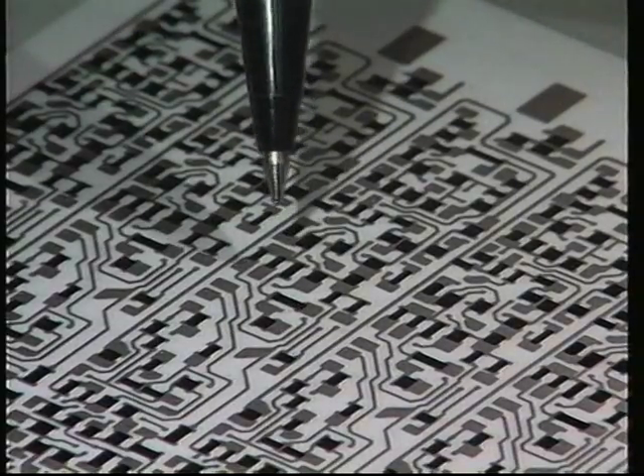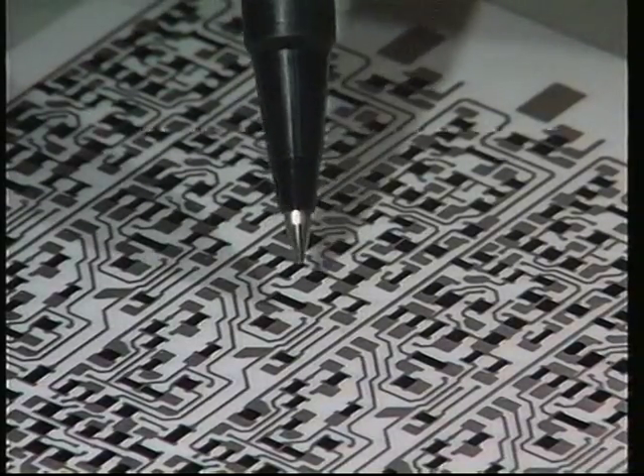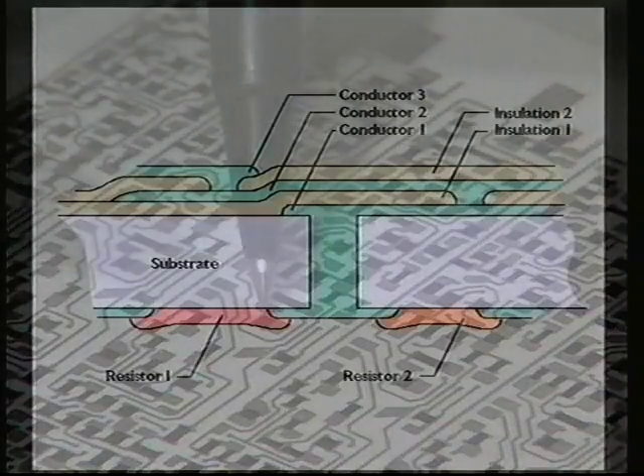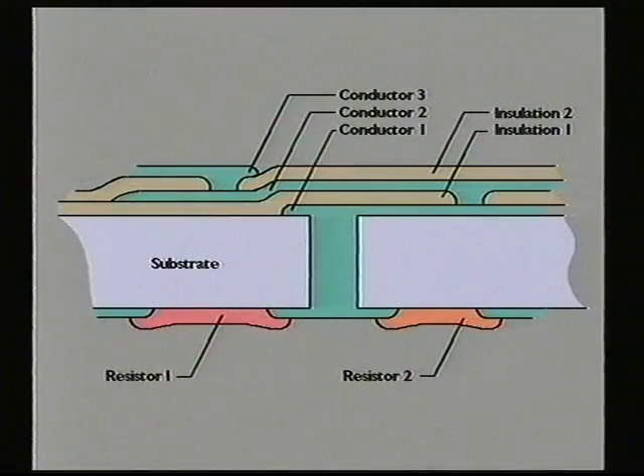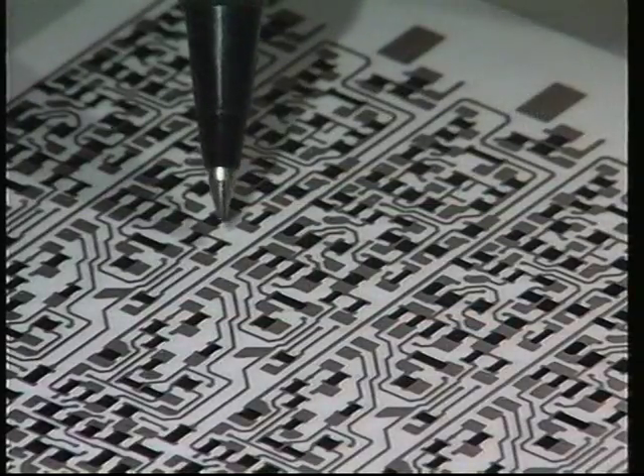Resistors are also added by screen printing. They are made on the reverse side with electrical contact through metallized holes in the substrate. The geometrical shape of the resistors and the concentration of metal oxides in the paste, like ruthenium oxide, will determine the resistance. The available values range from 0.1 to over 100 megohms.